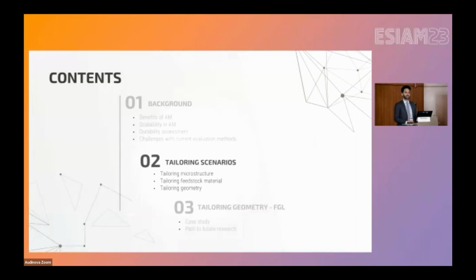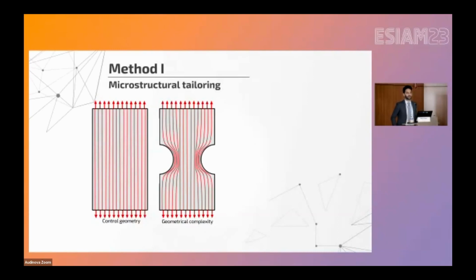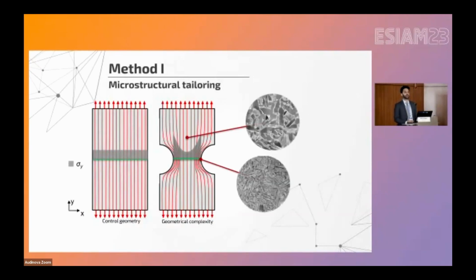That leads me to the second part of the talk, tailoring techniques. Of course, the first tailoring technique that I would like to talk about is microstructural tailoring. Consider this simple case. I've taken this from my lecture, so it's the easy case to say it. A simple plate and a plate with a semicircular notch. We have stress concentration at the edges of the notch. Those are the sources for fatigue initiation. And in fatigue, we know finer grains are favorable for the location where you have expected crack initiation. On the other side, when we have fatigue crack growth, coarser grains are more resistant. So what we want is a microstructure that is fine at the critical locations and coarse where the crack is going to propagate.